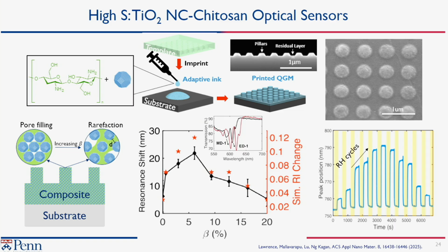In this case, we started with chitosan because it's a moisture-sensitive material. And we can also do the imprinting into these composite mixtures of organic and inorganic materials. And we could tune their relative compositions. And we found that at one particular composition, we could get the largest shift between, say, a low humidity and a high humidity state. So we could get the biggest sensitivity.